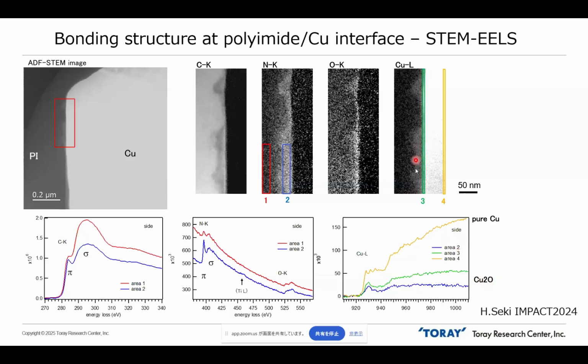We can also find copper intensity inside the polyimide, around here. Around here means area 2. In area 2, the peak structure is almost the same as area 3. So even inside the polyimide, copper is diffused, and the diffused copper is oxidized. Then next, let's see the carbon and nitrogen peak structure. Area 1 means inside the polyimide. Area 2 means around the interface between copper and polyimide.